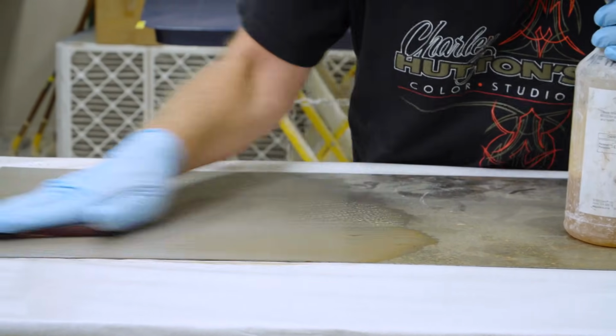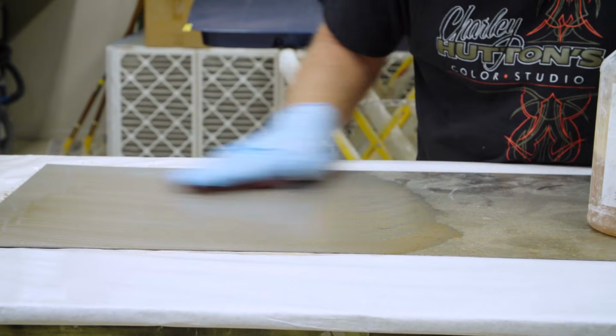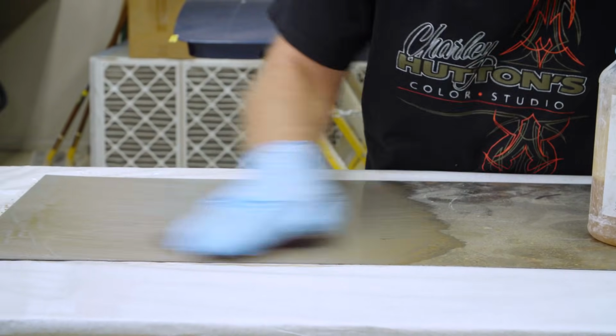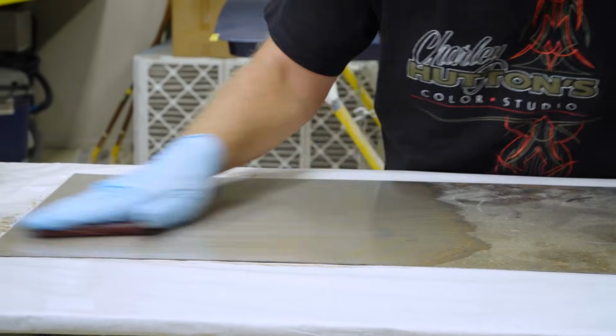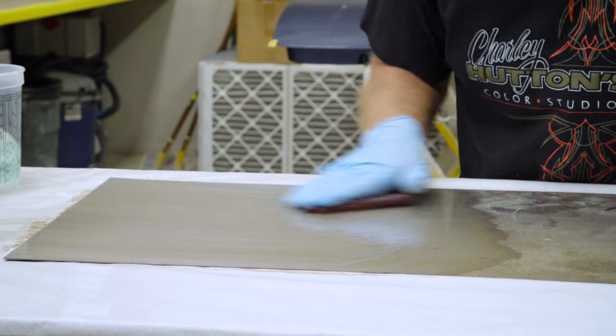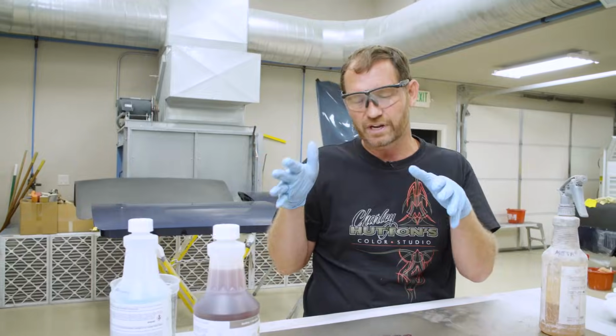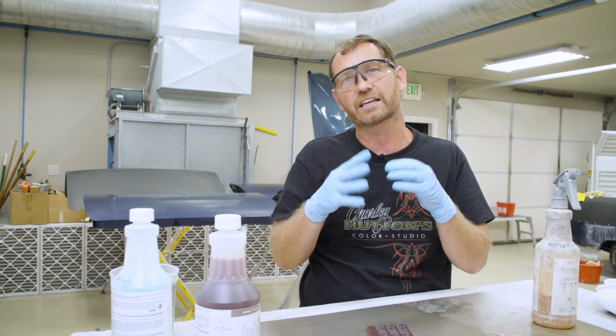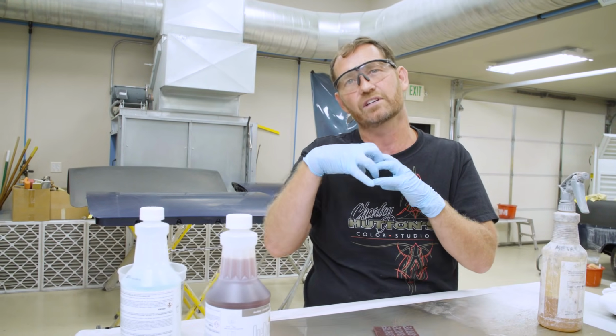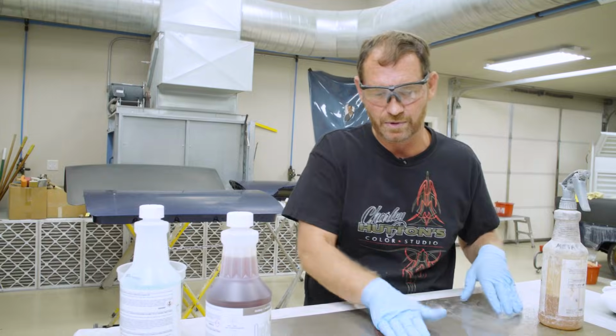Now what's going on here as you're scrubbing this, it's cleaning the surface rust off, but the acids in the 579 are actually etching into the metal surface. So what you're creating is these crystals that, when you put a sealer, an epoxy sealer on top of that, it gives you a great adhesion between the epoxy and the bare metal.